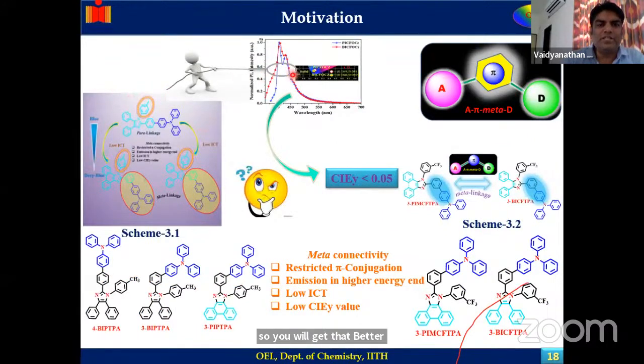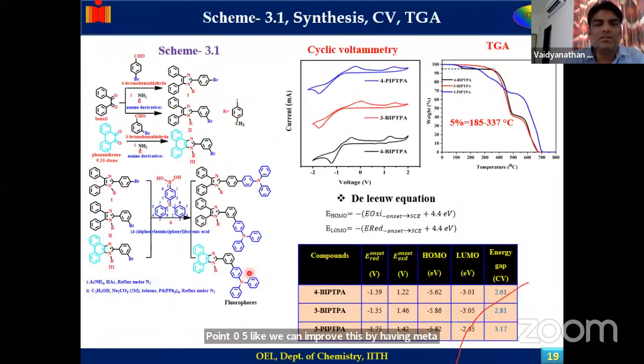So even though we got 0.05 in the previous one, we can improve this by having meta connectivity. So in that case, we synthesized meta connectivity and para connectivity. Para connectivity is giving less, but in meta connectivity, you get a good number. And then you have cyclic voltammetry, which has been used to calculate highest occupied molecular orbital as well as lowest unoccupied molecular orbital values. And the TGA has been used to find out whether these materials are stable, because when we are using this for the vacuum deposition, your material should be stable. If it is destroyed, then one cannot use them in OLED.